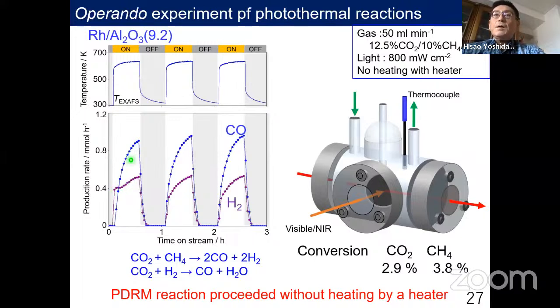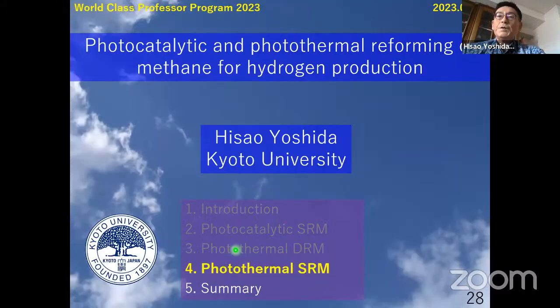It means the high temperature activates the metal catalyst, and the metal catalyst gives the products CO and hydrogen. The DRM gives equivalent molar amounts of carbon monoxide and hydrogen. However, the next reaction, CO2 plus hydrogen, also occurs to promote carbon monoxide formation, so the carbon monoxide is a little bit higher than the hydrogen. However, anyway, in this system, we can warm the catalyst by the photo energy.